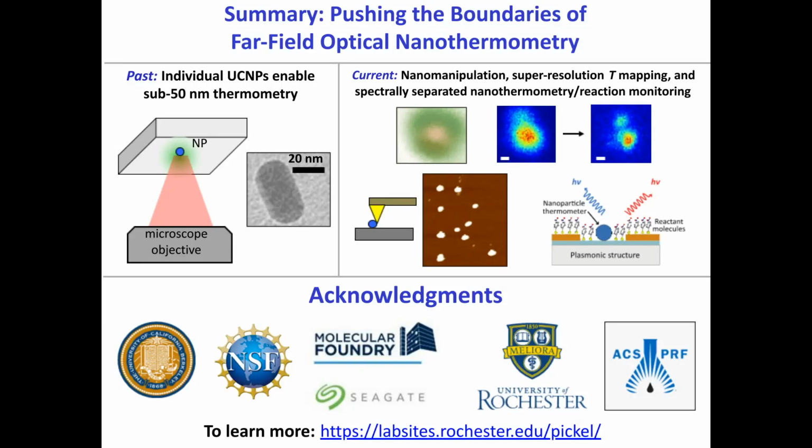A similar idea is to work at low excitation intensities, where even small changes in the excitation intensity will not give you this big apparent temperature change. So that's another way to avoid these effects. But even if you need to work at higher excitation intensities, and perhaps you cannot guarantee that the excitation intensity is held constant, just being aware of these effects, you can calibrate them by doing the excitation intensity sweeps that we did, and then take that into account so that you understand what is really a temperature change and what is this non-thermal artifact.